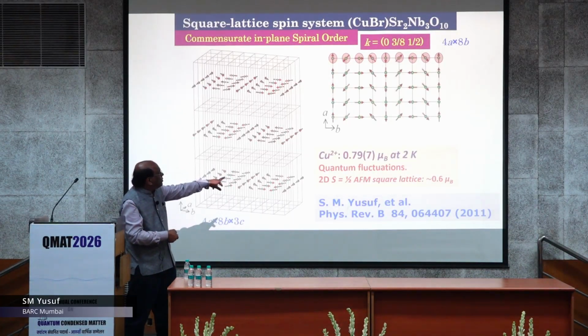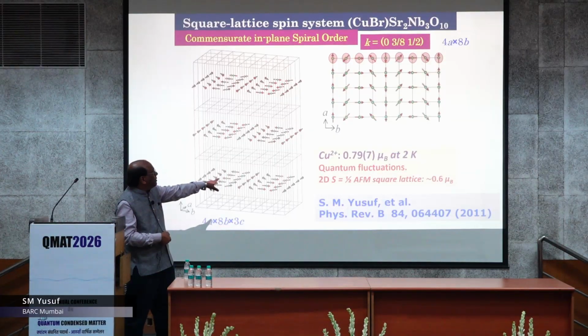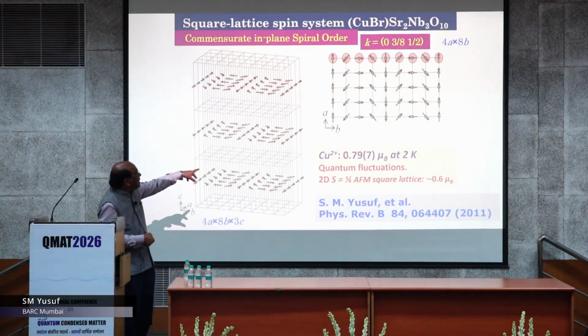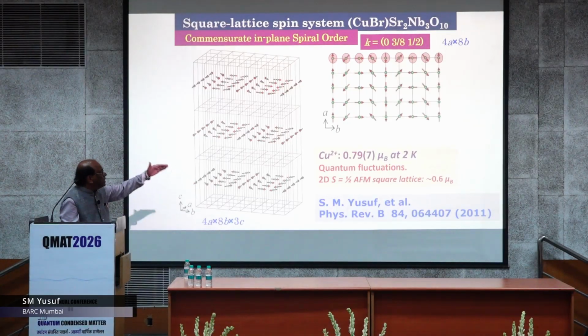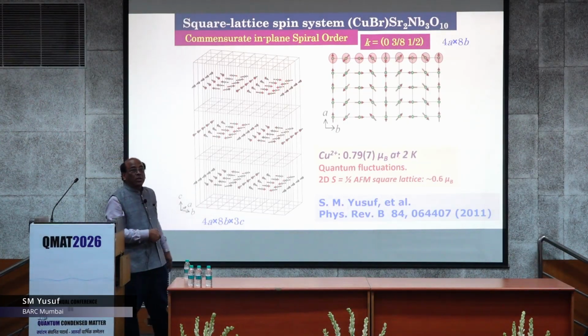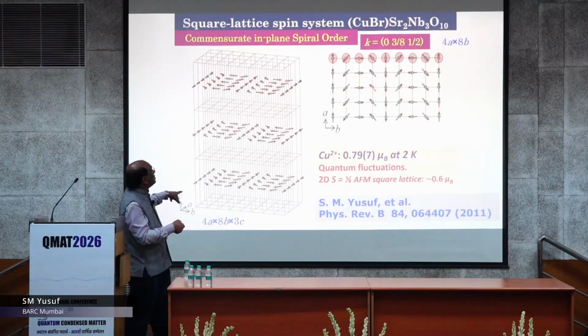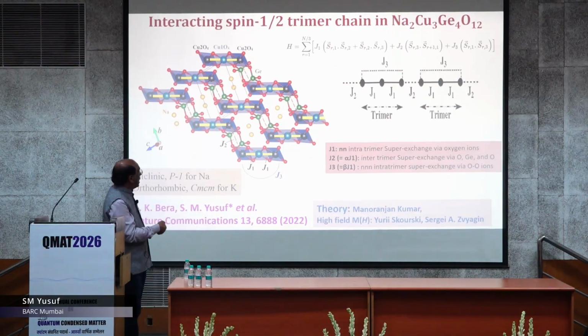But the message is that the copper spin, what we measure, comes only to 0.79 Bohr magneton. Theoretically, the quantum fluctuation gives 0.6, so it is very close to that. So that means this 1 Bohr magneton is reduced to this kind of value due to quantum fluctuation of this square lattice of copper spin half.